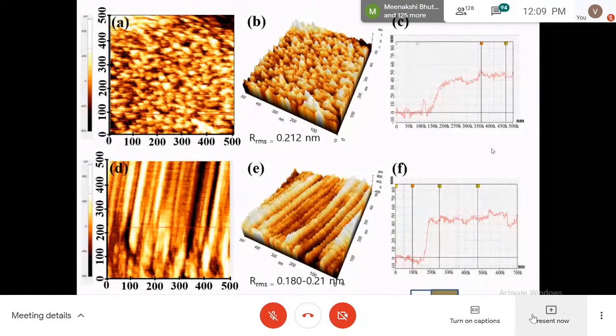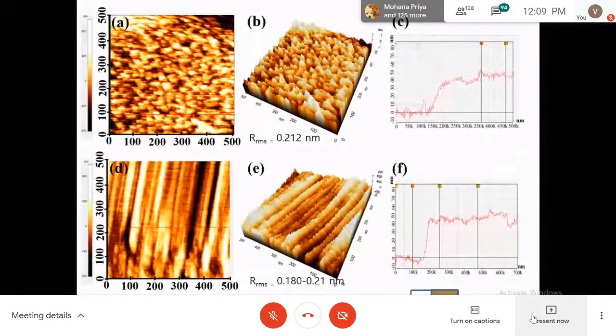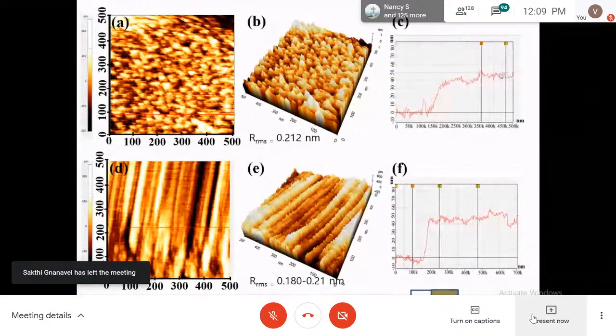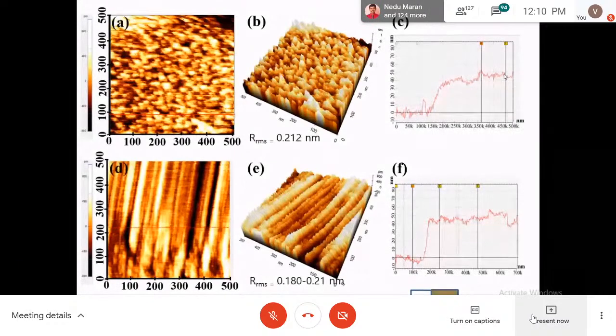The bottom one shows the alpha step, which is kind of an electrical scan that uses a laser to scan from the uncoated area to the coated area. When it is scanning in the coated area, there is an increment. So in this region there is no coating, and when the coating comes, it gives the corresponding thickness. When the profile is stable, we can take it as a measurement of the thickness. This is around 40 nanometer for 7.5 minutes, and for 10 minutes it is around 45 nanometer. A 5 nanometer difference was there.